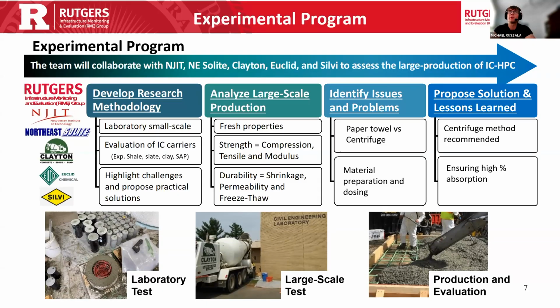So that's shrinkage, which relates to the cracking potential, the permeability of the material, so that's RCPT and surface resistivity, as well as freeze-thaw testing, which is a big concern with these lightweight materials historically. So we tested the paper towel method versus centrifuge method, and we tested different stockpiling methods, and we tried to replicate that as much as possible in the lab, how it would be in the field. So the solutions were, we proposed the centrifuge method, and really the prep is what makes this technology excel. And you can get additional benefits by doing very good prep and just get more water into the mix.